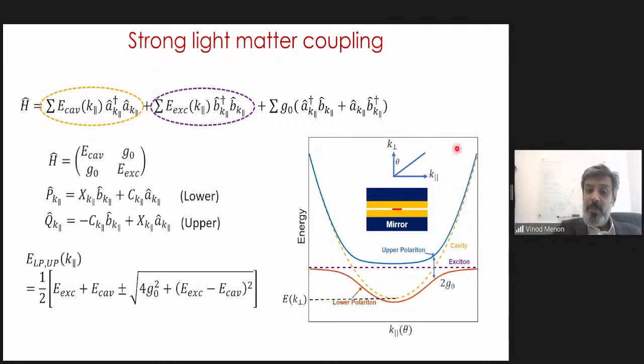Of course, when you get into the strong coupling regime, at this crossing point, you get new hybrid states, which are called the lower and upper polaritons. Now, a very analogous phenomenon happens when you take two harmonic oscillators and you couple them, and you do the normal mode splitting. You get the two normal modes of the system, and of course the splitting depends on the coupling strength, the damping rates of the individual oscillators, and so on. So there is a classical analog of this whole process as well. And then you find the solution to the problem.